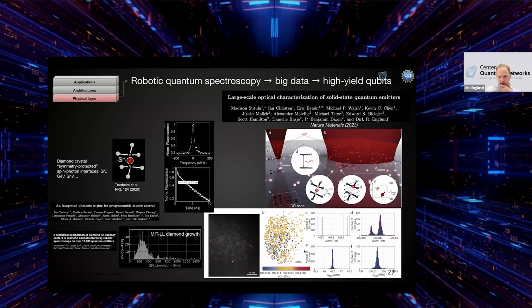So here is the line width measurement, and there's a spread of the atomic transitions, but the line widths themselves, you can see here a histogram of these kinds of measurements. This is for silicon vacancy center, which has a roughly 3 times faster decay time, so the line width is 3 times larger. So take 20 megahertz times 3, 60. So this here would be line width limited. This is the best as you could possibly do around here. And you see that they're a little bit worse, but not much worse than the quantum limited line width allows.